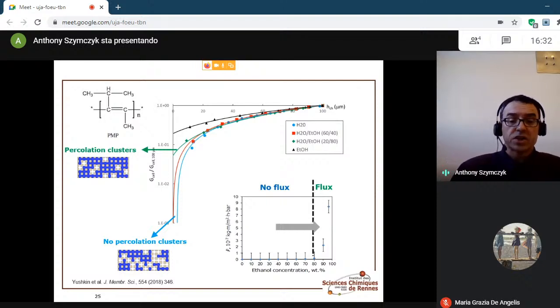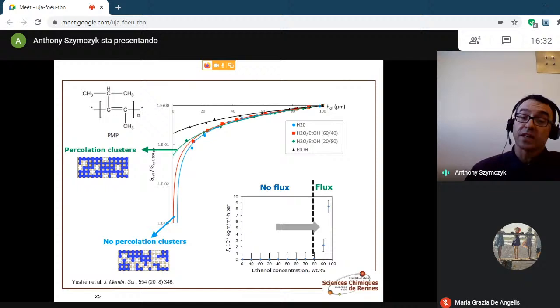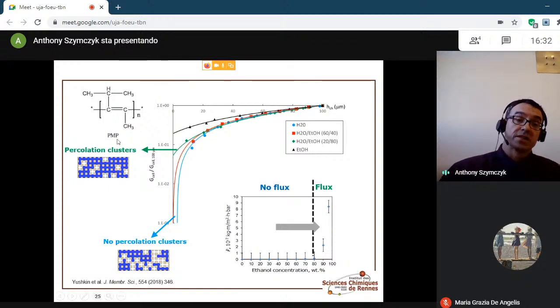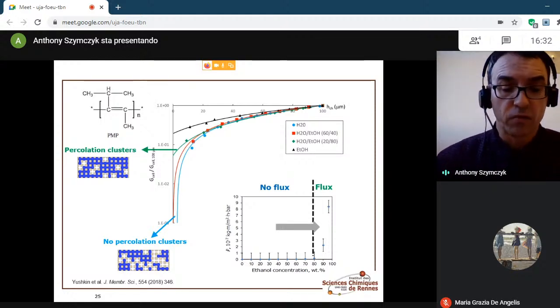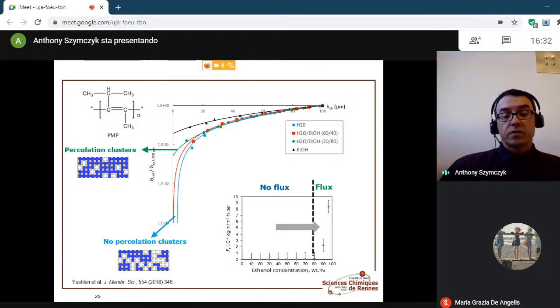Volkov's group has shown that polymers with intrinsic microporosity, such as PMP for instance, are impermeable to water even when pressures of several tens of bars are applied through the membrane, even though this polymer absorbs a significant amount of water. They also showed that liquid transport through these membranes remained impossible with water-ethanol mixtures until a threshold concentration of ethanol was reached in the mixture.